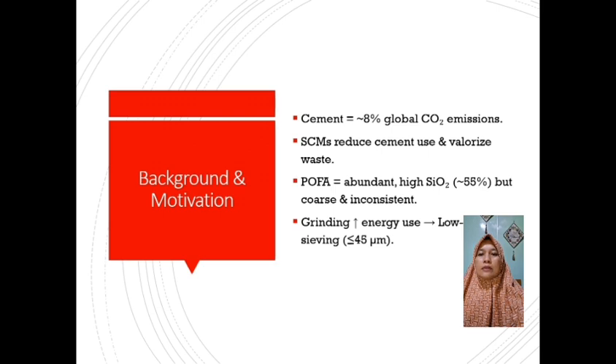In this study, we propose a low-energy approach using sieved ultrafine POFA with 100% passing the ASTM number 325 sieve, or lower than 45 micron, to assess whether it can exhibit adequate pozzolanic reactivity without any grinding process. From the literature review, we identified several gaps.